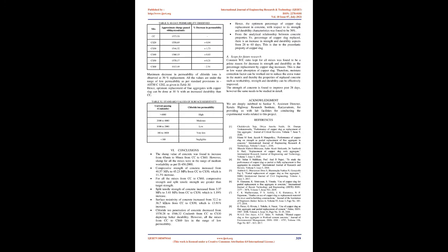All the values are under the range of low permeability as per standard provisions in ASTM C1202, as given in Table 11. Hence, optimum replacement of fine aggregates with copper slag can be done at 30%, with increased durability compared to CC. Table 11: Standard values of surface resistivity. Current passing. Chloride ion permeability.